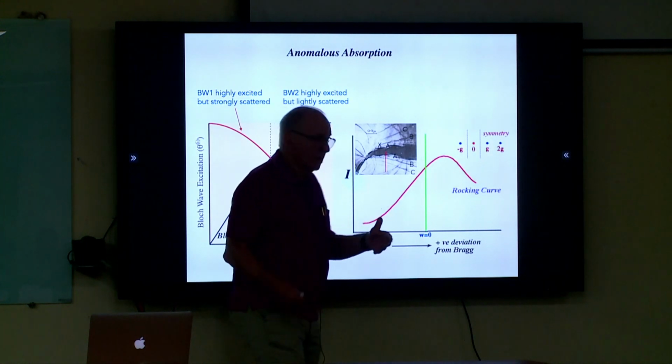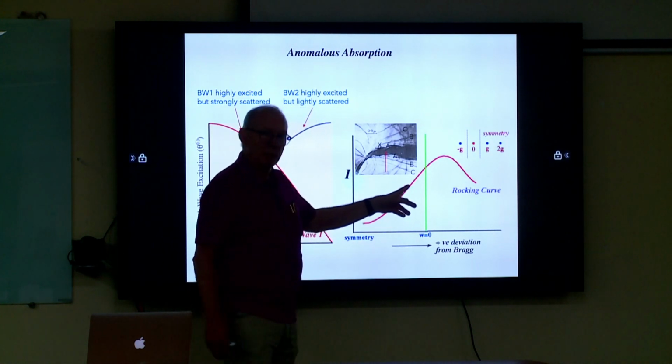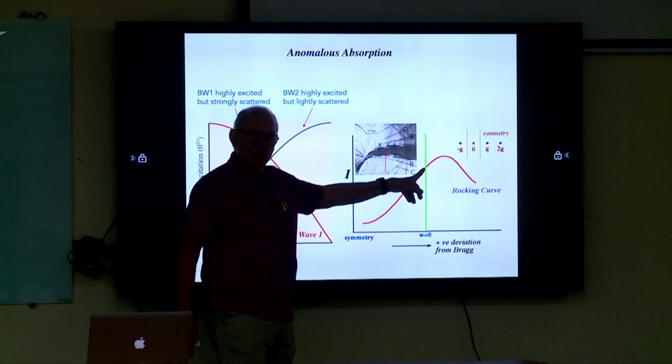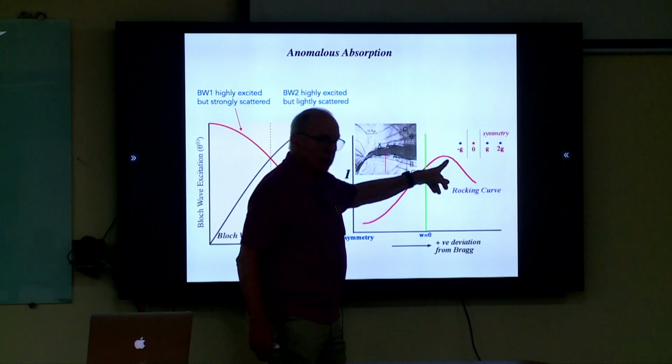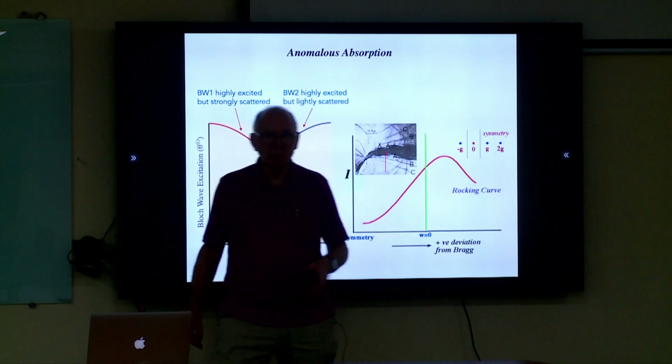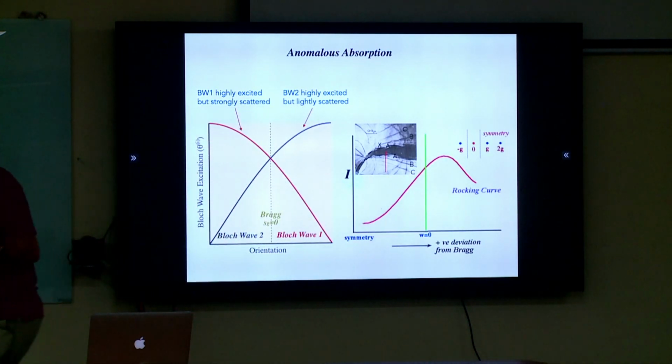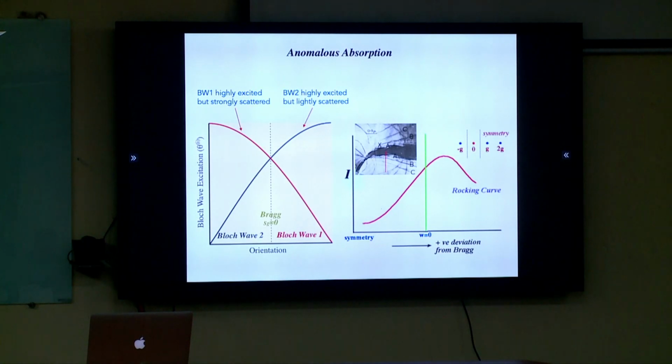And that's what we want. That's why, when we were at the Bragg condition, we saw pretty grungy contrast. And as he deviated from Bragg, it got better and better, right? Because the contrast offered by the dislocations was increased because of this effect. Now, again, I'm not a fan of all this mathematics, but I am a fan of understanding what I'm seeing. And we can understand now a lot of what we've already noted we couldn't do with the kinematical theory.